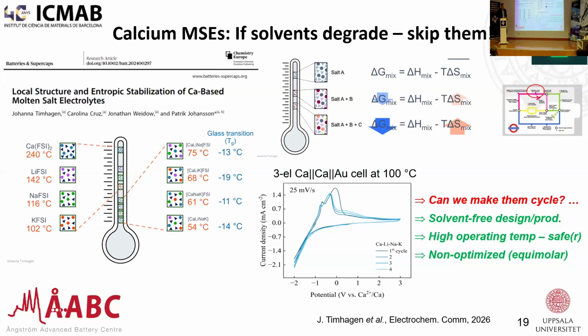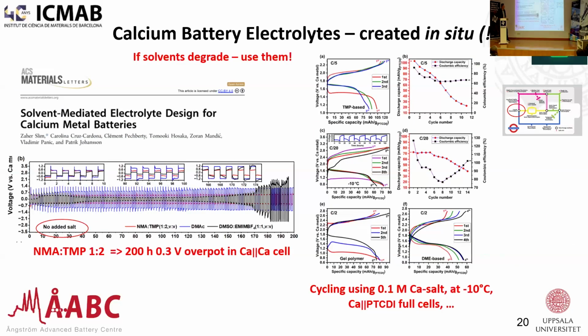Now we run it at 100 degrees Celsius just to get the speed up a little bit in the viscosity, because these are very highly viscous systems. But nevertheless, we actually can make it work. So that is something that one can say that, okay, we skip the solvents totally because they can degrade, they can be a risk or so. The other approach to do is that, well, if solvents degrade, let's use that fact. Let's think of solvents as a source for your electrolyte.